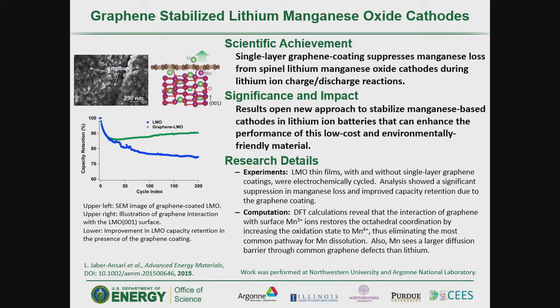Now there's a third approach, from our Northwestern colleagues, Mark Hersam and gang. Mark's specialty is working with graphene, and he was looking at LMO electrodes sputter deposited on steel. They're crystalline, forming these boulder-like structures, a fairly complex morphology. But nevertheless, somewhat surprisingly, when you put one or a couple layers of graphene on the electrode surface, that allows one to retain a lot of the capacity that would normally be lost without it. So experimentally, we found three different ways to limit the loss of capacity of these LMO cathode materials.